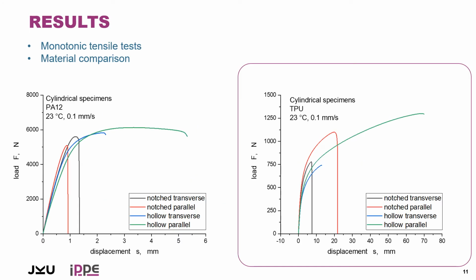The first results of the monotonic tensile test, in a very classical way: load displacement curves for polyamide 12 and also for TPU material with the different orientations, transverse and parallel, and notched and hollow cylindrical specimens. And as we expected, we see the differences between notched and unnotched, and of course we see significant difference between the printing orientation, transverse and parallel.